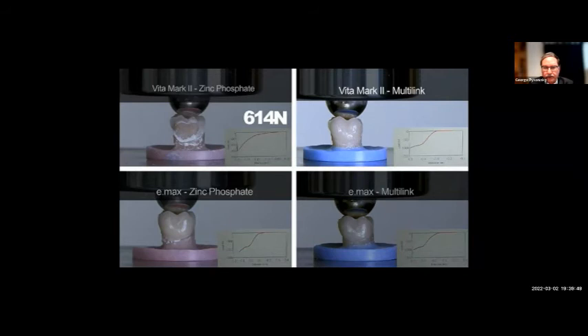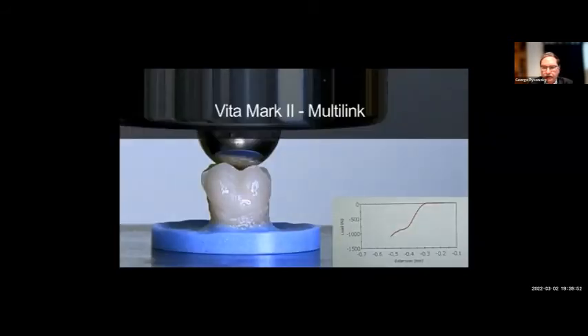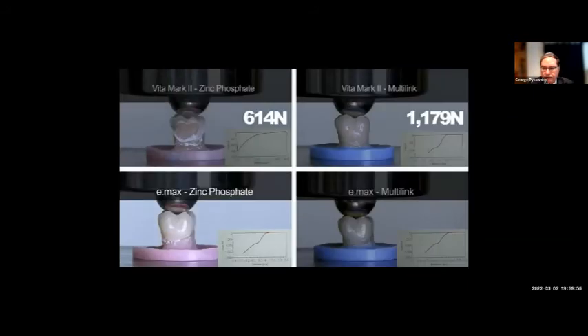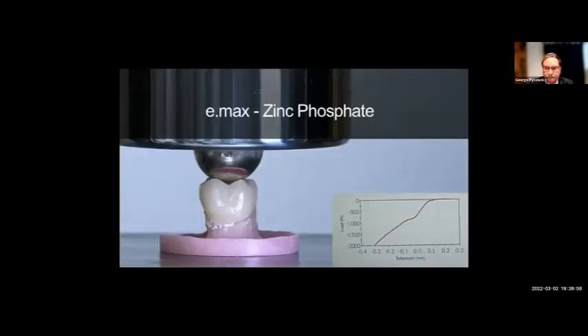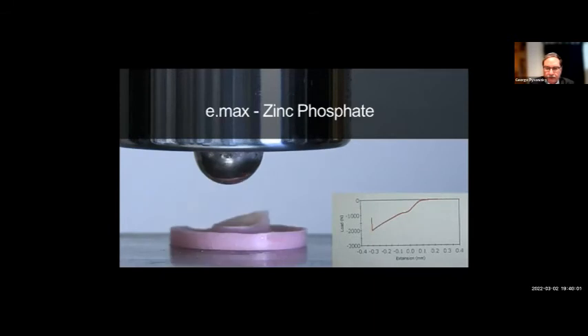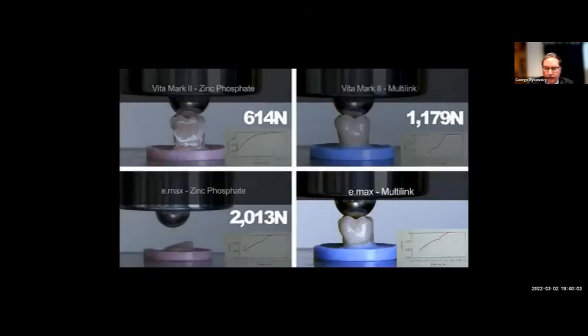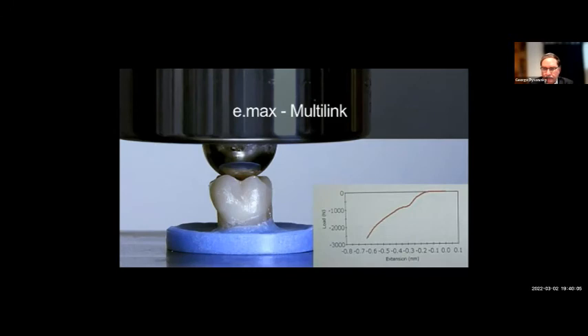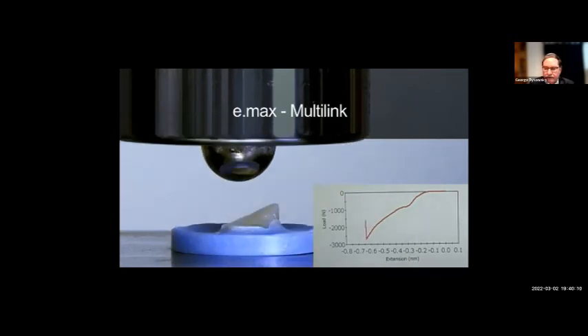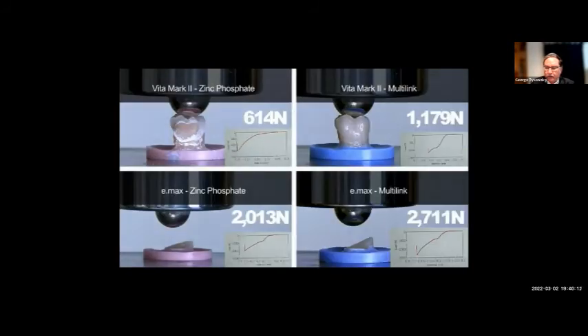We got a 600 Newton loading there. We took a weak ceramic with a high strength cement. We doubled it to about 1200. We took a high strength material like Emax and a weak cement, and you could see we went to about 2000. And then we went to a high strength ceramic and a high strength composite cement, and we went to about 2700. So again, what we use and what we use for cementation plays a very critical factor on the success of that final restoration.